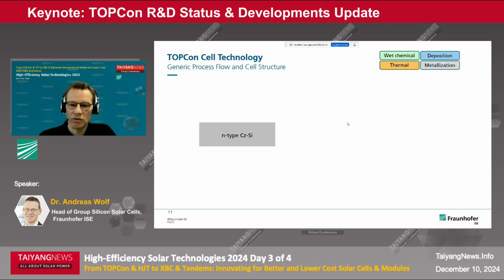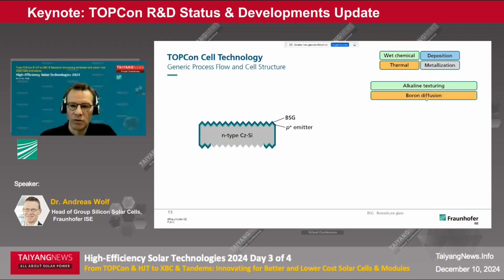Now looking at the industrial cell process and structure here, I brought a generic process flow and cell structure to introduce all you to this process sequence. Most of you are familiar with this, but we go through the sequence quite fast. You start with an N-type wafer, which in the first step is texturized. Then a boron diffusion forms the P+ emitter, and the borosilicate glass still remains on the surface, and you have some wraparound in this process which needs to be removed. And this is done in the next step in chemical edge isolation.